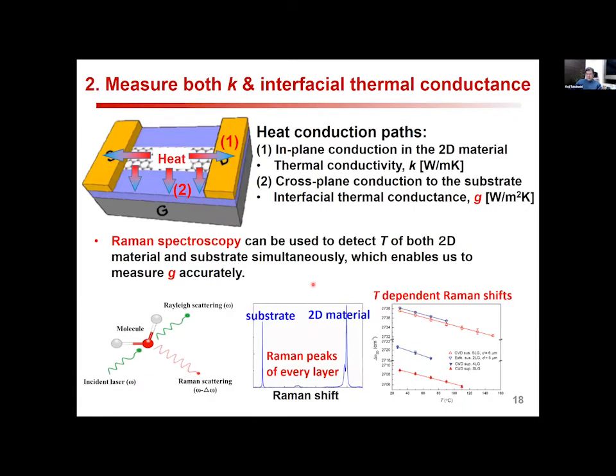The previous slides treat only in-plane conduction, but here let me explain how to evaluate the cross-plane conduction. This number 2 heat. Raman spectroscopy can be used to detect the temperature of both the 2D material and the substrate. I mean, the temperature of this material, and also the temperature of the substrate. Then we can measure the interfacial thermal conductance G just between the two-dimensional material and substrate, because the Raman signal can be obtained simultaneously from the different materials.